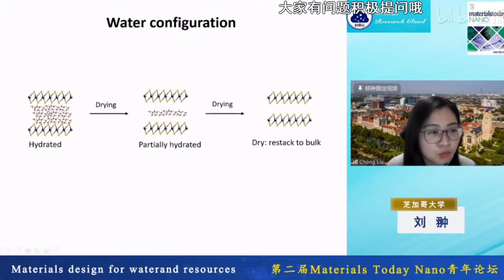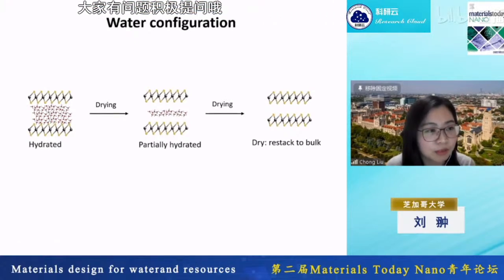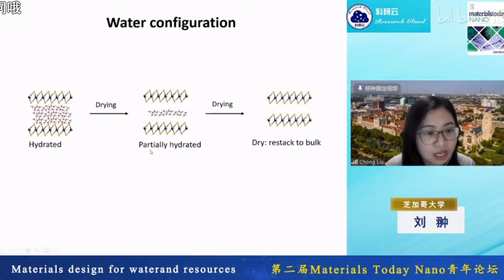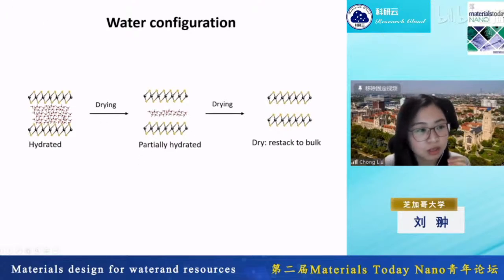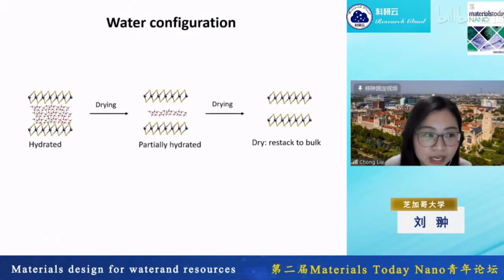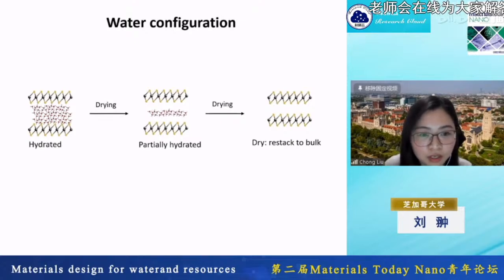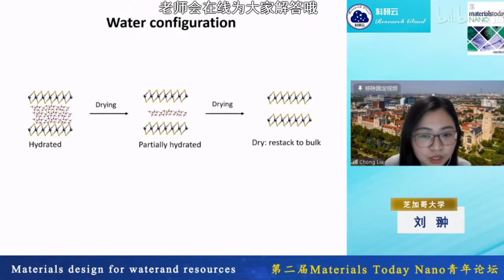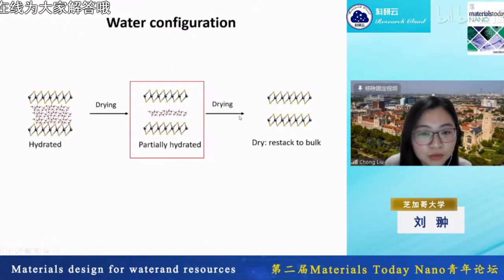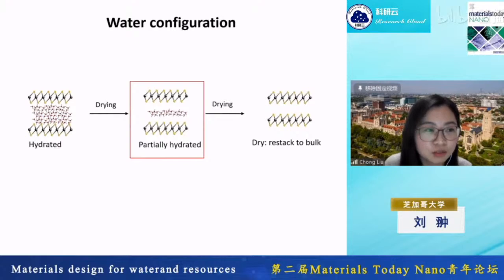But these water layers are too wide, and it can't separate anything because of the size. So you have to decrease the amount of water to a sweet spot, the limit you can decrease to, but you don't want to go to the region where it's totally dried. Because if it's totally dried, the molysulfide will just restack to the bulk form of the material, which doesn't allow anything to come in. So this is the critical point. You want to create a layer spacing at the sweet spot.